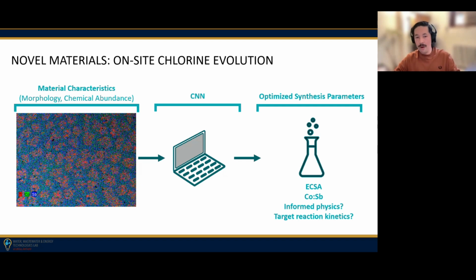And then when we're annealing it, we're using 600 degrees C, so we have to use a big oven, which takes up a lot of energy. So what we're trying to do now is use the data that we have, whether that be through our SEM images, our scanning electron microscope images here, which tell us about morphology, or our EDS images. You can see how our SEM images match with our EDS images, and this is telling us how cobalt is distributed on the electrode surface or how antimony is distributed along the electrode surface.